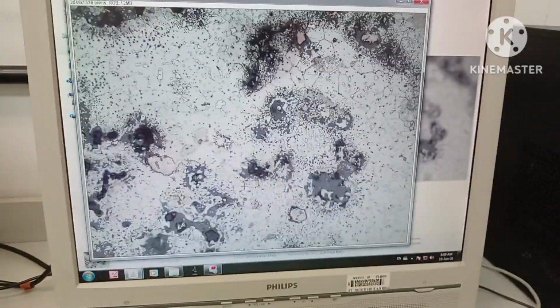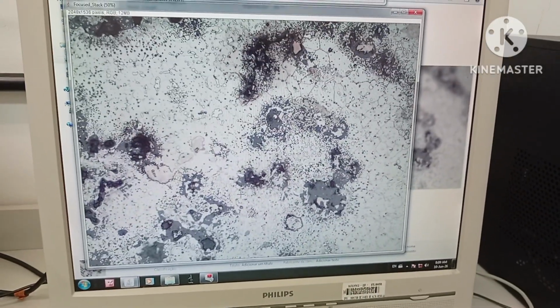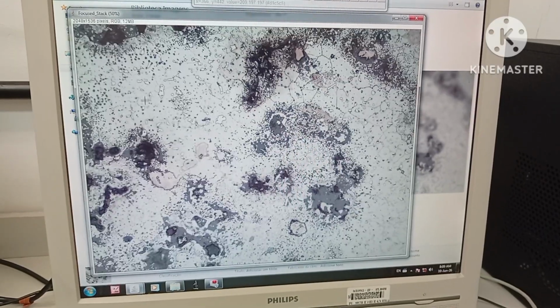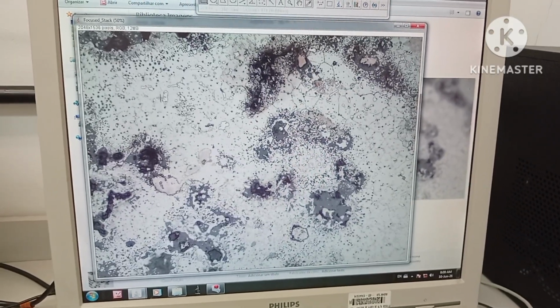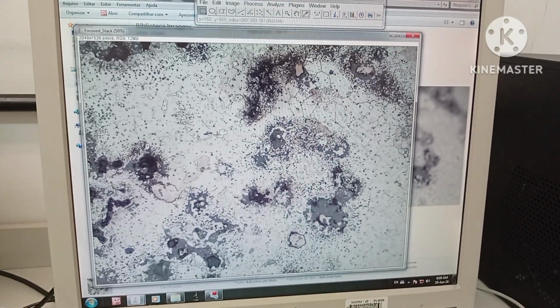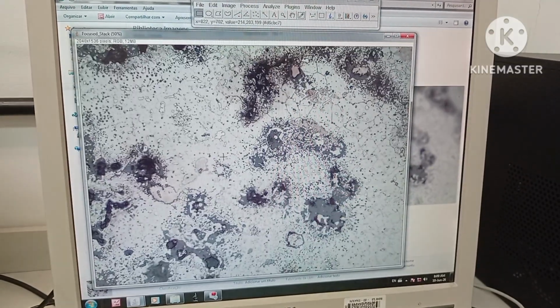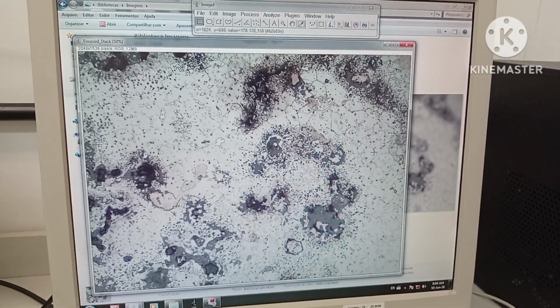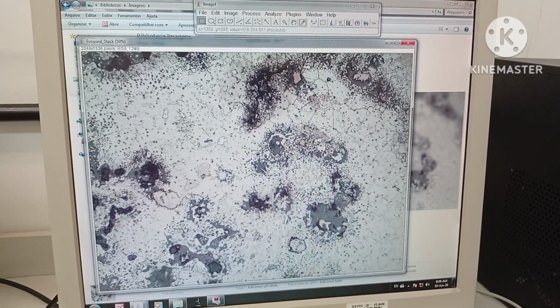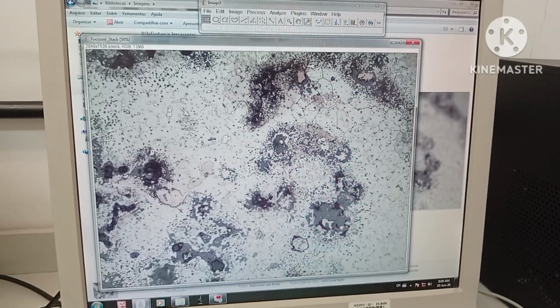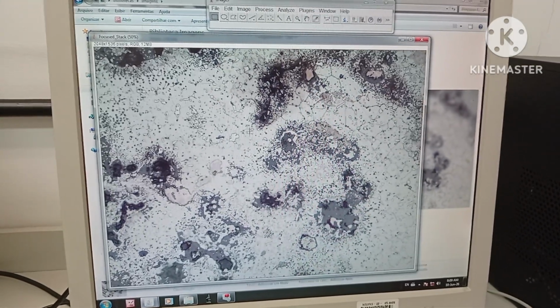That's here for Nital. You can see the carbides from the cross here on the ImageJ, and you can also see some grains close to the oxidation points due to the heat treatment here.